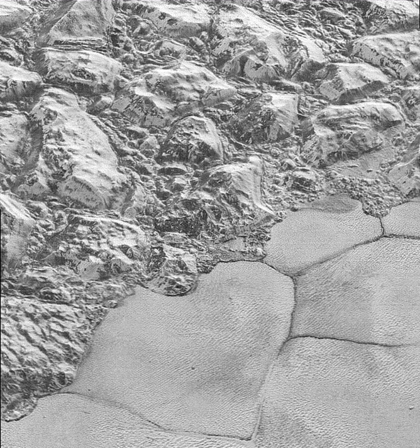Methane. Solid nitrogen can crystallize with some solid methane included. At 55 K, the molar percentage can range up to 16.35% CH4, and at 40 K, only 5%. In the complementary situation, solid methane can include some nitrogen in its crystals, up to 17.31% nitrogen. As the temperature drops, less methane can dissolve in solid nitrogen, and in alpha N2 there is a major drop in methane solubility. These mixtures are prevalent in outer solar system objects such as Pluto that have both nitrogen and methane on their surfaces. At room temperature there is a clathrate of methane and nitrogen in 1:1 ratio formed at pressures over 5.6 GPa.